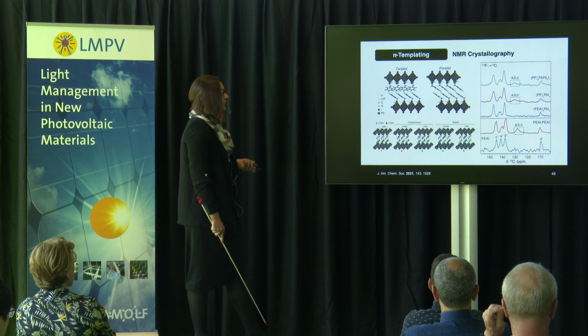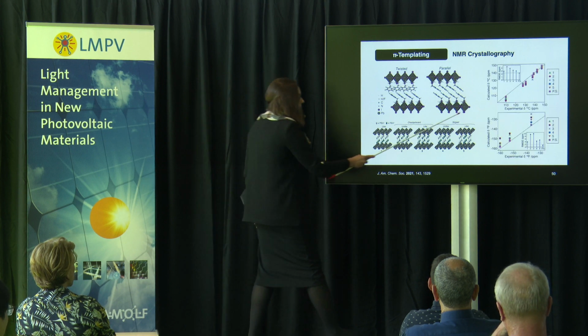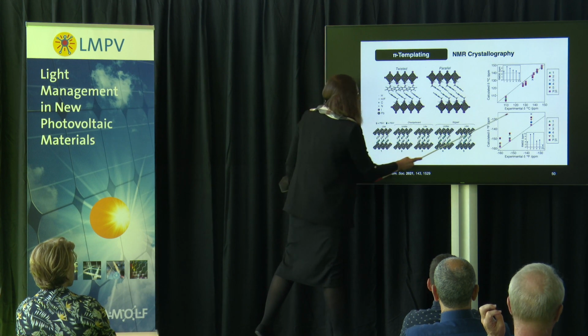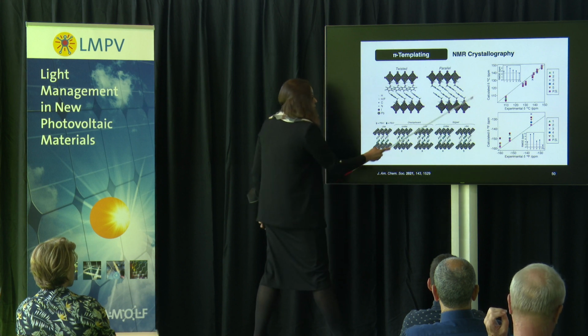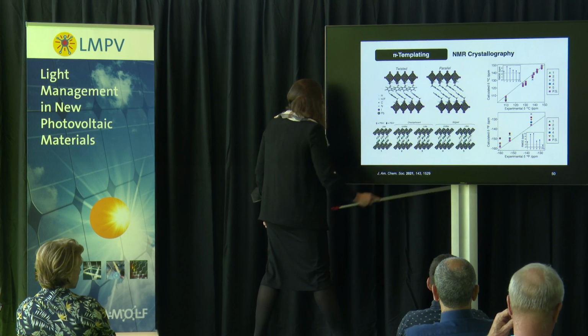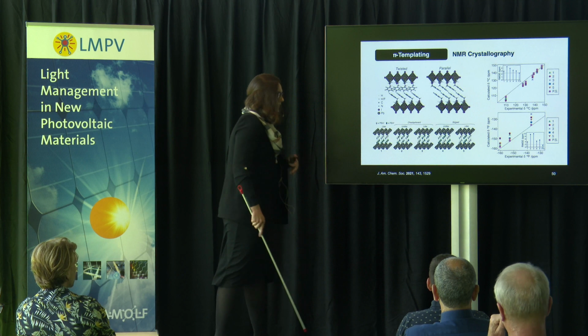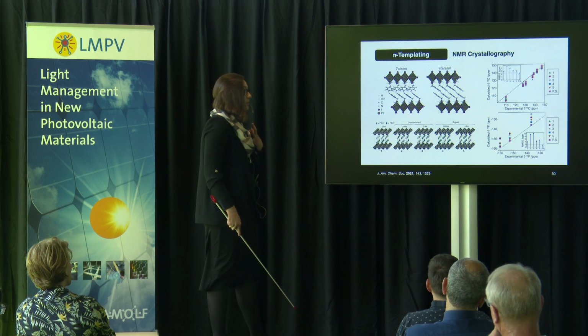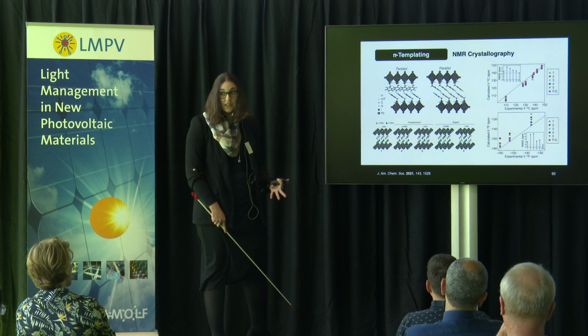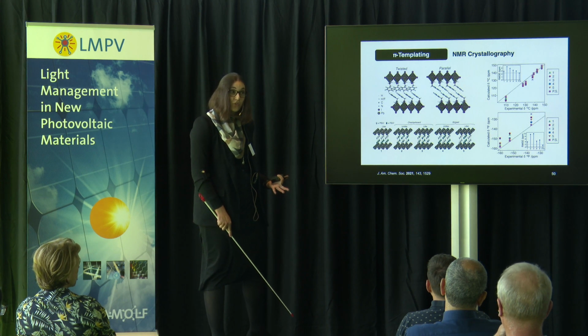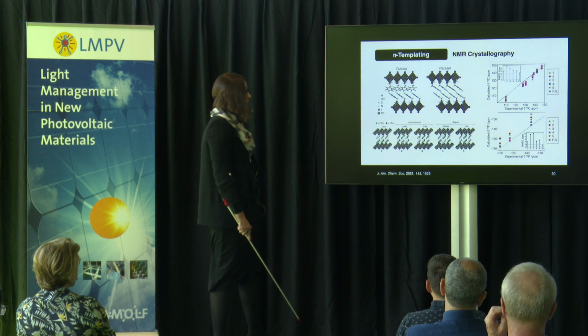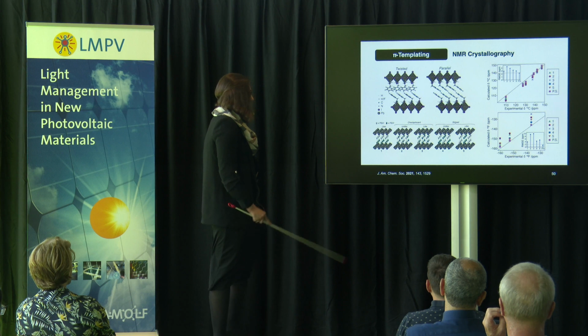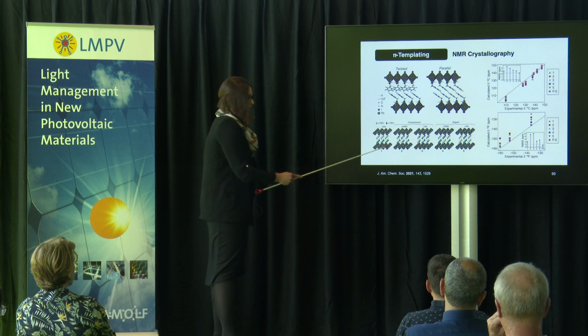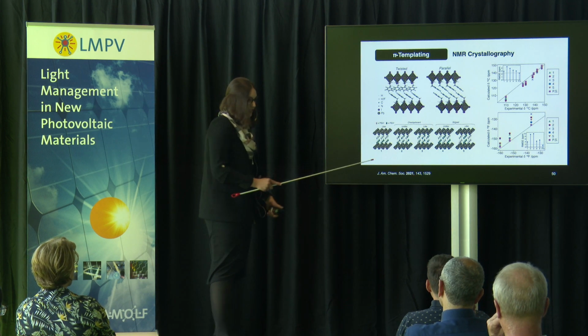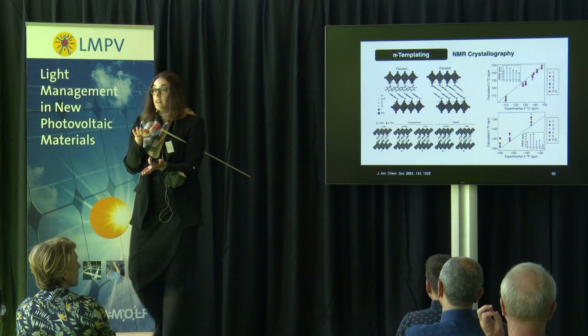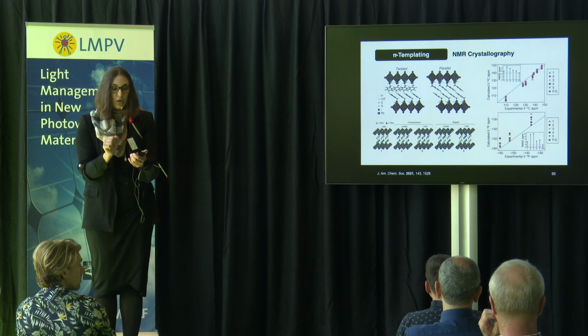structure, lead to these beautiful linear correlations between the calculated and experimental values for both carbon and fluorine spectra, and ultimately give us the answer of what is the most likely structure that we observe in these films or mechanosynthetically prepared powders, which based on these analyses is suggested to be the structure that is also the most thermodynamically stable or desired for our case, being this fully alternating arene perfluoroarene structure.